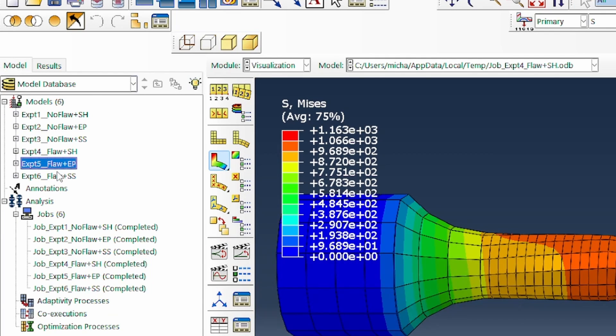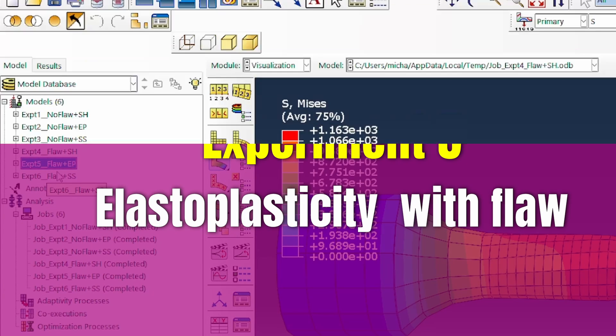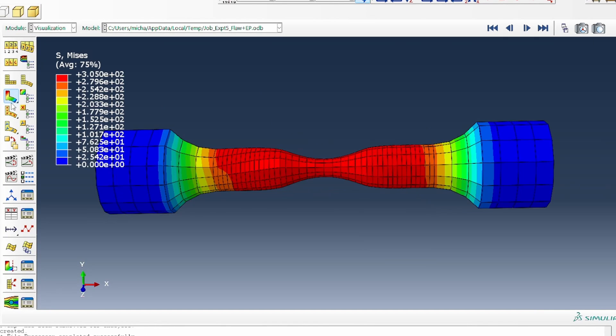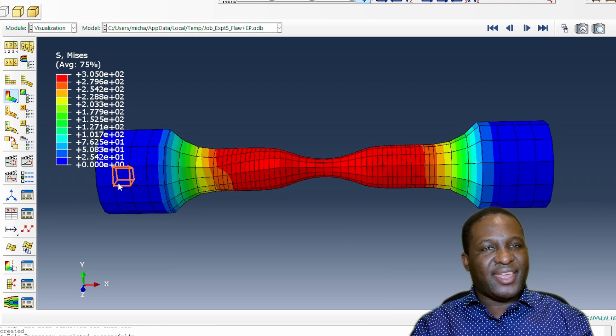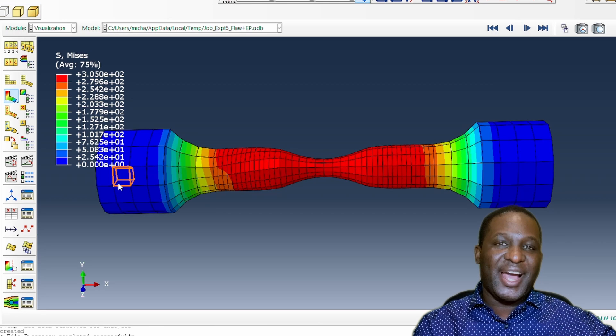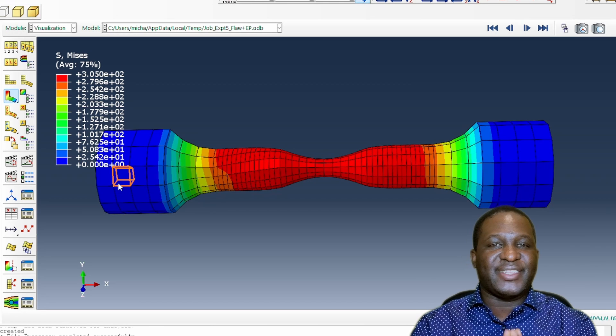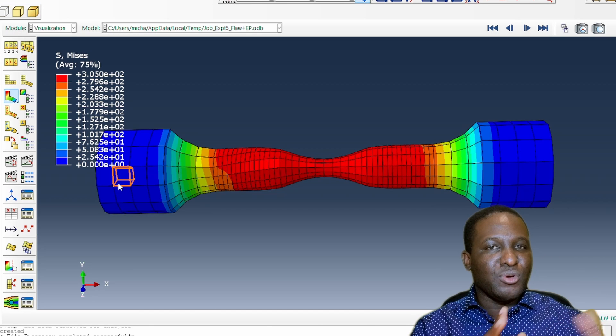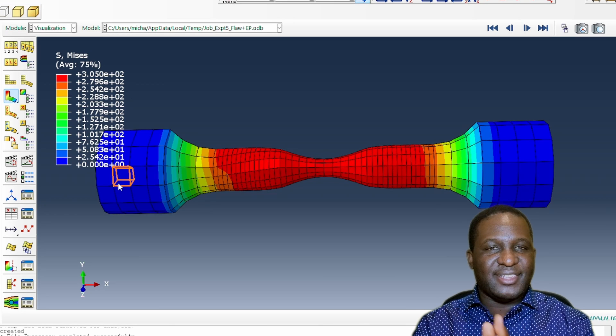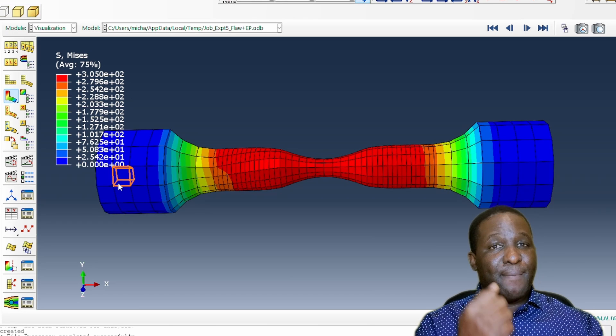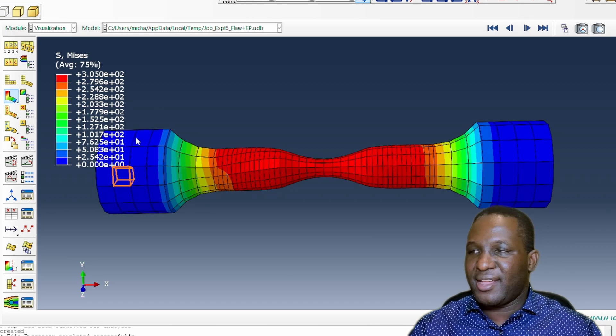Experiment five has a flaw with an elastoplastic material — no strain hardening, just a constant plateau stress after yield. Looking at the result, we now see necking because of the presence of the flaw. The flaw is what is triggering the necking, even without strain hardening in the material. This goes back to what Considère said: a flaw and decreased strain hardening are two principles that encourage necking.